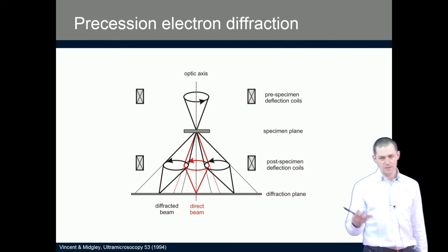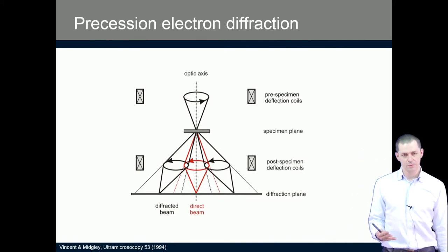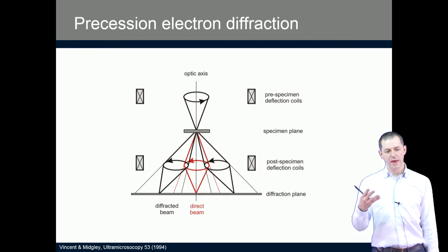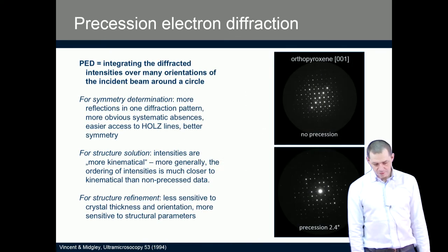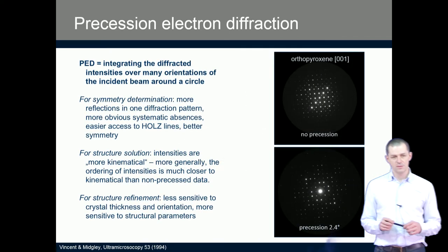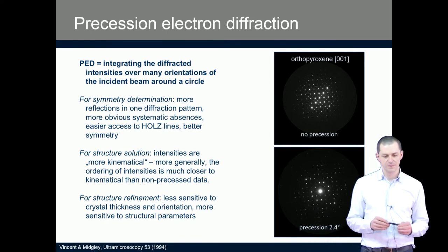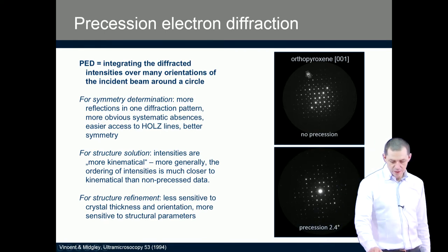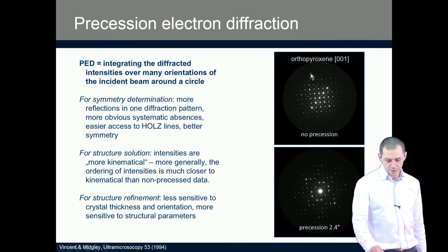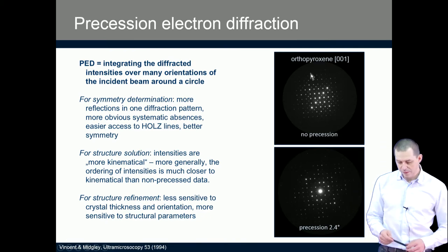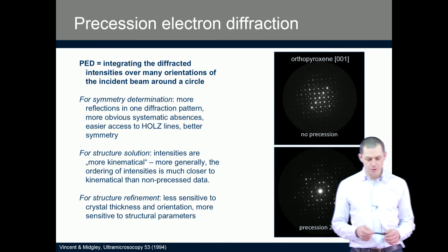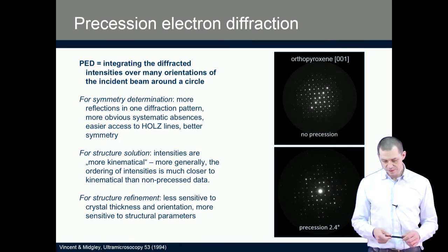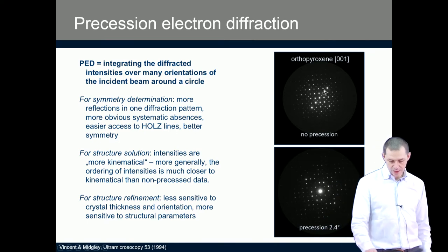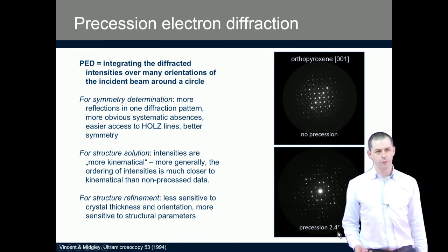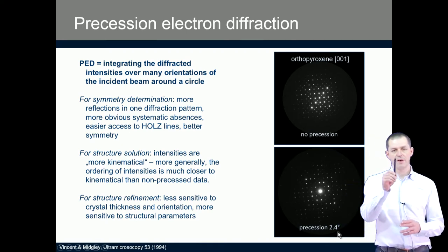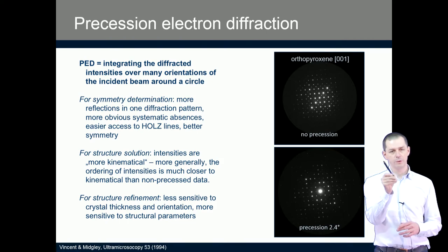At first glance, the diffraction pattern from precession electron diffraction looks the same as without. However, there are important differences in the distribution of intensities. Here is a diffraction pattern from the 001 orientation of orthopyroxene, a mineral silicate, without precession, and with precession of 2.4 degrees. That means that the half angle of the cone is 2.4 degrees.